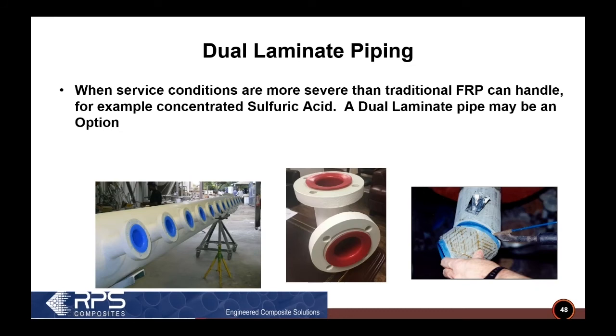So in this case, you've actually got two examples here. The pipe on the left-hand side is lined with FEP, and in the middle, it's lined with Kynar. And I say lined, but it's actually a little bit different than lined steel, because what we do is take tubing, Kynar tubing or FEP tubing, we embed glass onto the tubing, and then we lay up over top of it. So you get a bonded liner to the pipe. So the liner and the FRP are all in one.